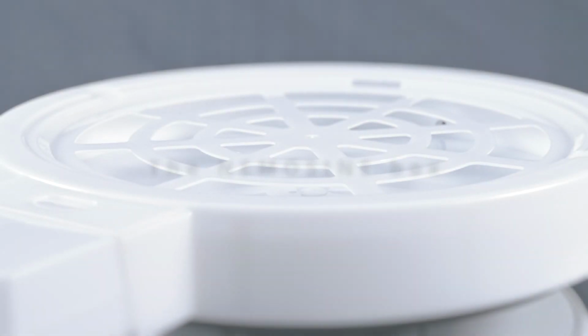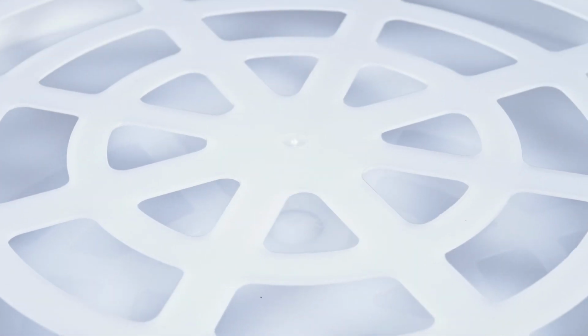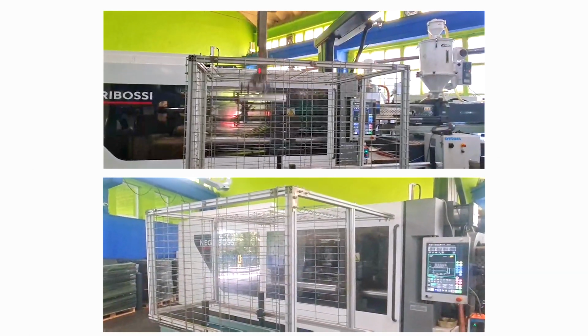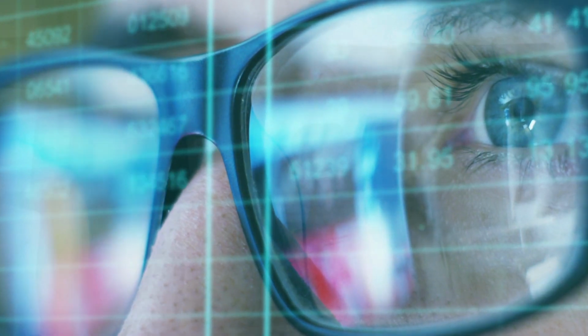The NEMOSINE package is made of polypropylene for its chemical resistance. It is inert and stable, a good water-vapor barrier, suitable for injection molding, and its price, a key factor for scale-up and commercialization. NEMOSINE has comprehensively characterized several grades of PP for injection molding, especially in terms of volatile organic compounds and phenols.